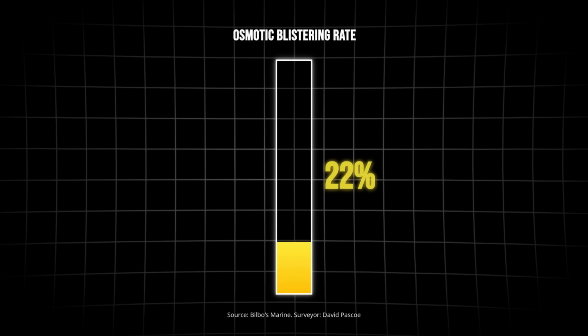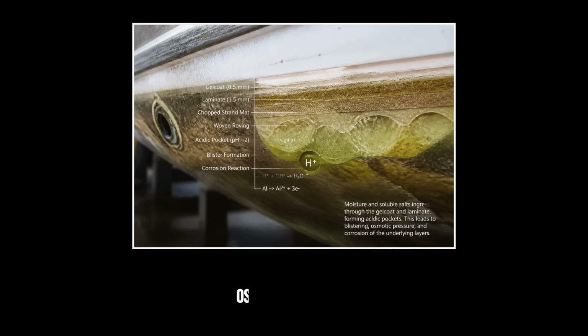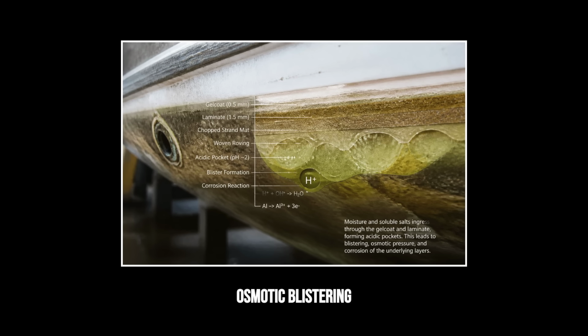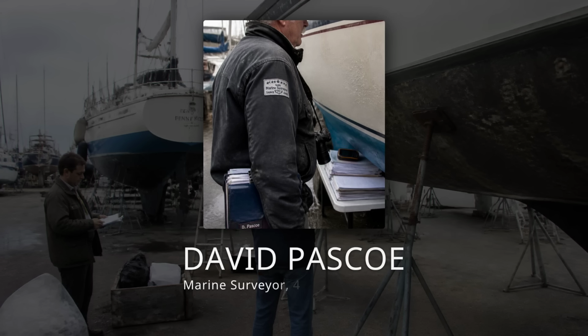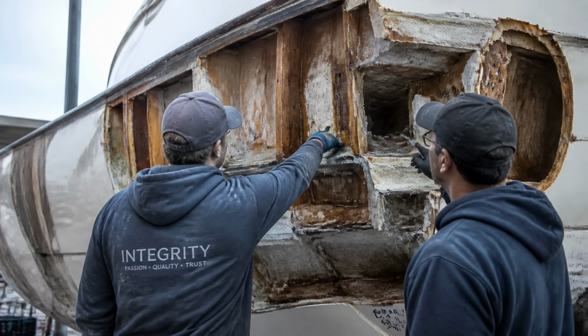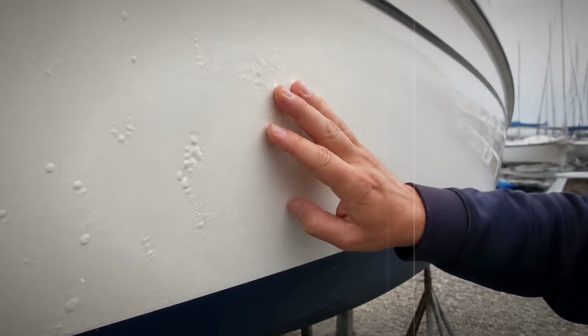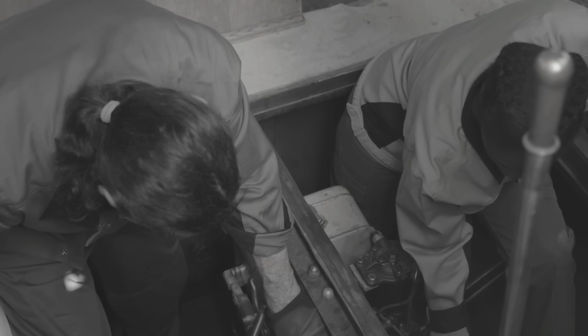1 in 4 fiberglass boats develops osmotic blistering, according to Bilbo's Marine. Water pushes through the gel coat, reacts with chemicals in the laminate, and forms acidic pockets that blister the hull from below. Marine surveyor David Pascoe examined roughly 4,000 hulls over 30 years. Fewer than 10 had serious structural damage from blistering. Most blistering is cosmetic. The repair is not cosmetic.